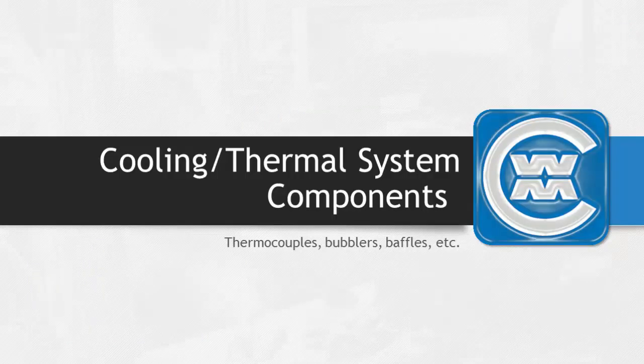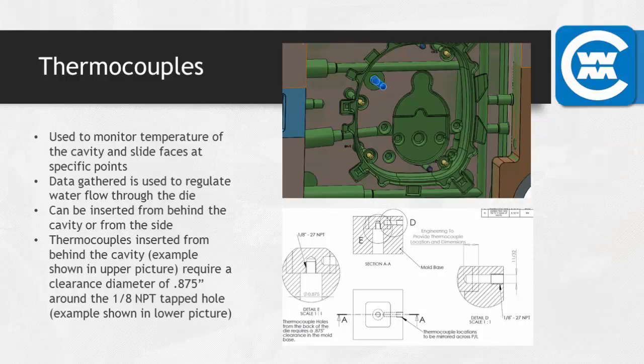All right, we'll get into the cooling and thermal system components at this point. So we'll start with thermocouples. These thermocouples are inserted into each half of the tool, sometimes into multiple areas. This helps CWM monitor internal temperatures of steel and regulate our process water. So a hotter than normal reading on a thermocouple indicates the steel is too hot. So water lines nearby increase in flow to cool that area down automatically. Similarly, if we found that the thermocouple was reading too low, we would decrease the flow of water in that area, and then the die would begin to heat up as you make shots over time.